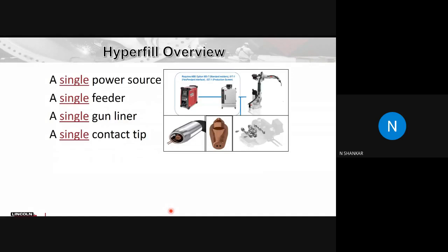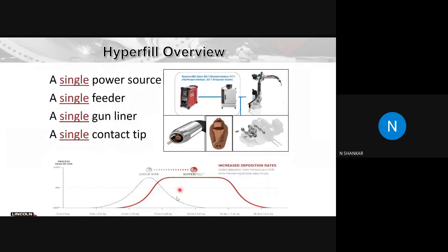How is Hyperfill a hybrid process and different from tandem? Because it's got only one single power source, single wire feeder, single torch, single liner, and single contact tip. Not just that, it's got only a single arc. But it gives you two-wire deposition, which means a 100% increase in efficiency of deposition. That's called the Hyperfill process for you.